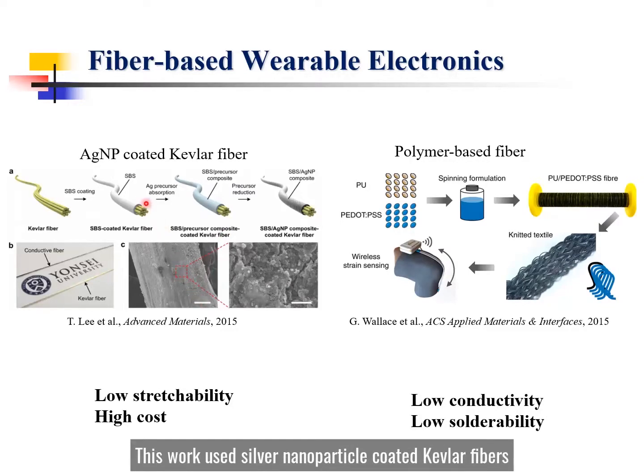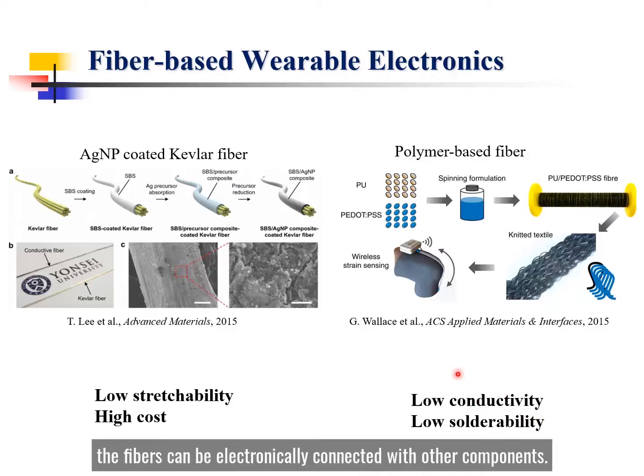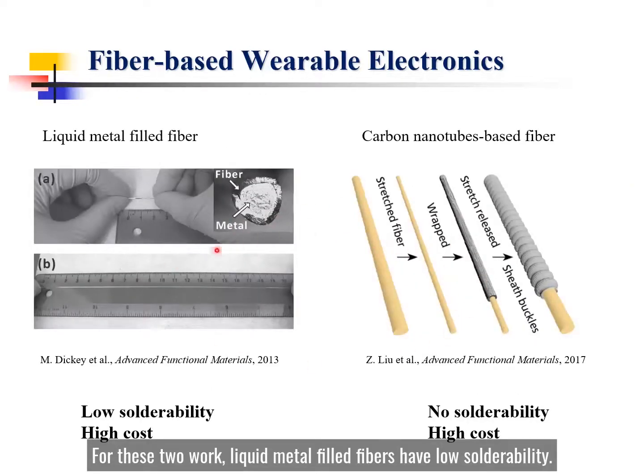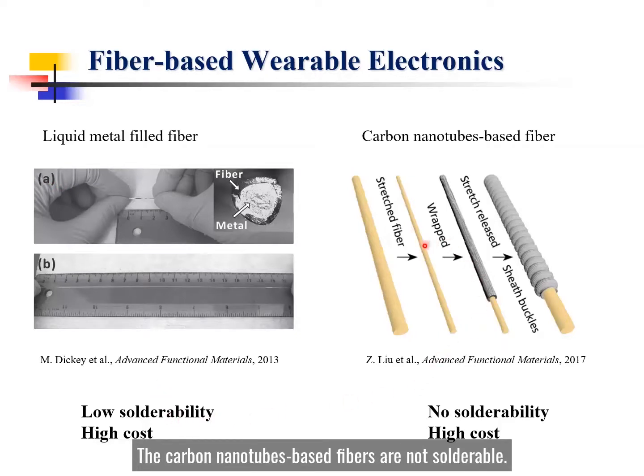This work uses silver nanoparticle-coated Kevlar fibers, and this work uses conductive polymer-based fibers. For this one, they have low stretchability, and for this one, they have low conductivity and solderability. Solderability is an important property to ensure the fiber can be electrically connected with other components. For these two works, liquid metal filled fibers have low solderability. The carbon nanotube-based fibers are not solderable.